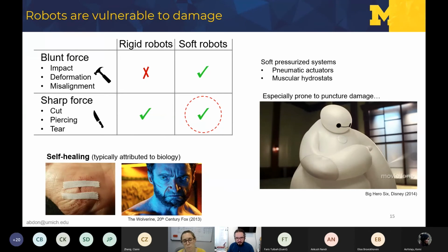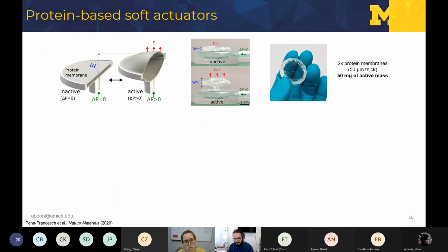And we developed a very simple proof of concept pocket actuator that consisted of two protein membranes that are joined at the edges here, and when this is pressurized, it inflates, exerting a normal force to the surface, right? And we tested this, to have damage and healing, and we didn't see any loss of performance, both in terms of force and in deformation, across several cycles of damage and healing.